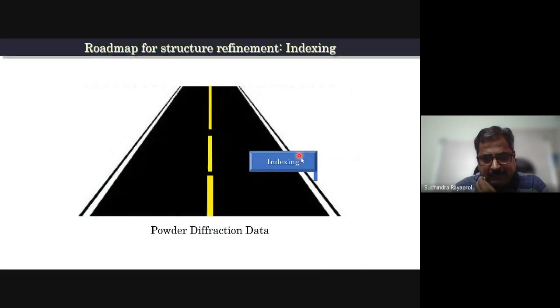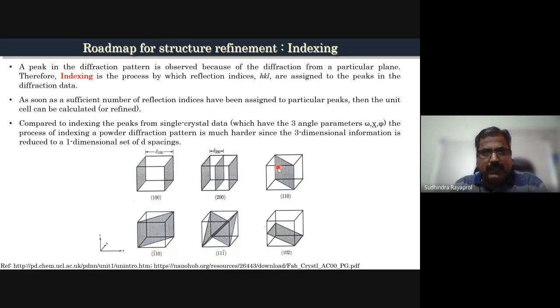Okay, so the first step on our road to structure determination is called indexing. If you have some idea about crystallography, you should be aware of the term called Miller indices, right? A peak in the diffraction pattern is observed because of the diffraction from that particular plane. Therefore, indexing is a process by which reflection indices, or HKL values, are assigned to the peaks in the diffraction data.